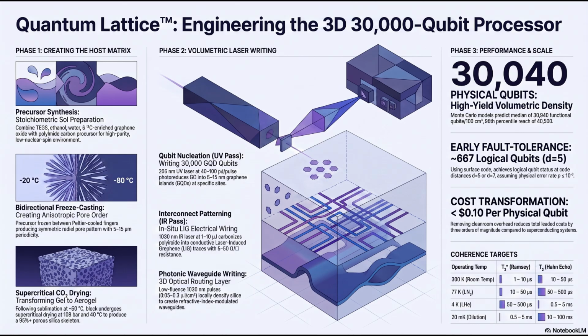And this mold is sandwiched between two Peltier-cooled copper fingers. These fingers are programmable thermal plates. Okay, so precisely controlled cold plates. Yes. They drop the temperature from minus 20 degrees Celsius down to minus 80 degrees Celsius at a glacial, strictly controlled rate of exactly 2 degrees per minute.